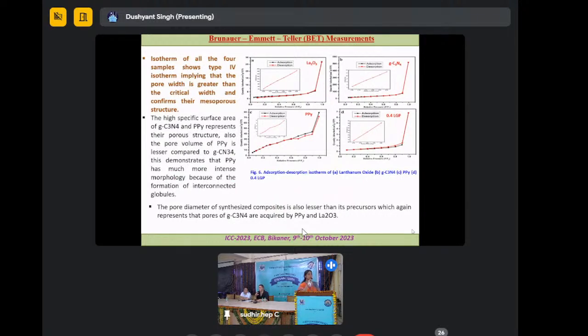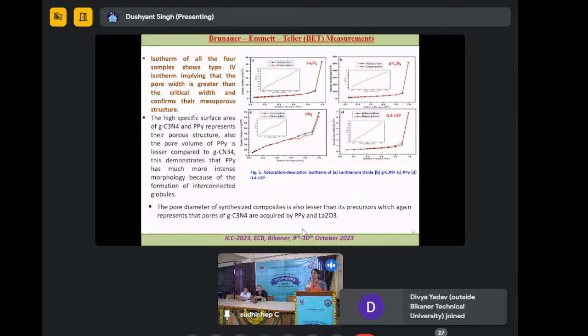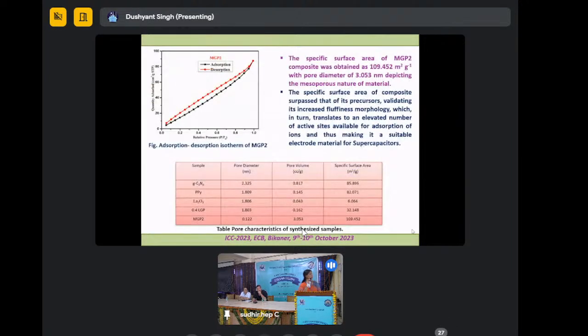And this is a BET measurement just to find out the pore size and specific surface area of the pure graphitic carbon nitride and polypyrroles. But after doping, what is the effect on the pore size? Because for the supercapacitor electrode, the main property is the specific surface area of the material. So we need to find out whether the doping of lanthanum oxide and magnesium oxide affects the pore size and pore volume of these basic graphitic carbon nitride sheets. So here we can see in the pictures, Doctor, and this table shows.